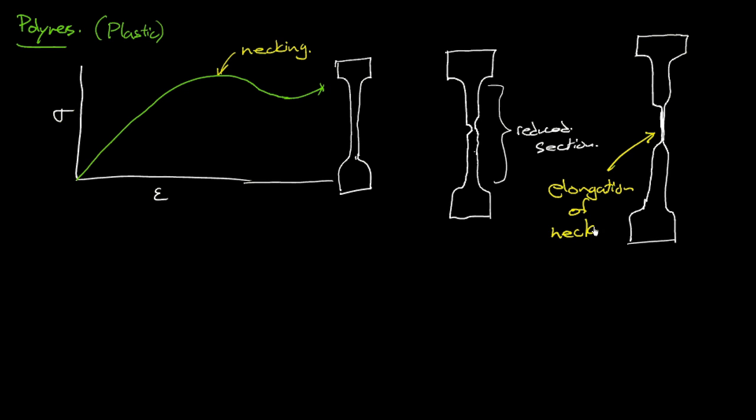So that should be a little surprising to you if you are familiar with the mechanical behavior of metals, where in contrast, as soon as it necks, the stress goes up way too high there, the metal can't get strong enough fast enough, and it fractures. Whereas in a polymer, there's something, and clearly there has to be some mechanism in here that's allowing the polymer to get stronger more rapidly than the stress is increasing due to the smaller cross-sectional area.